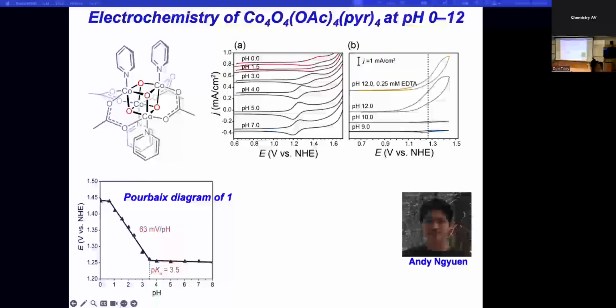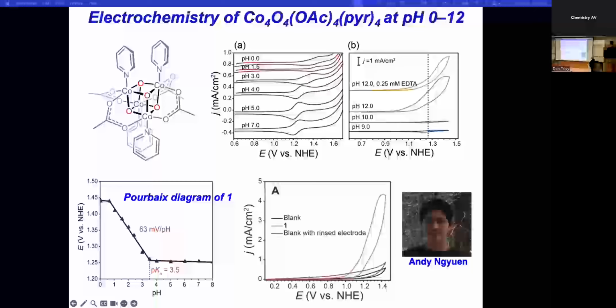But then at pHs that are higher, above about 9, you start to see this catalytic wave. And you can also tell that oxygen is evolved in that process. So what is happening there? Well, you can take the electrode out and rinse it and see that activity go away. And that's one indication people have used, that the species in solution is actually doing the electrochemistry. But that's not really proof that the species is doing the electrochemistry, right?